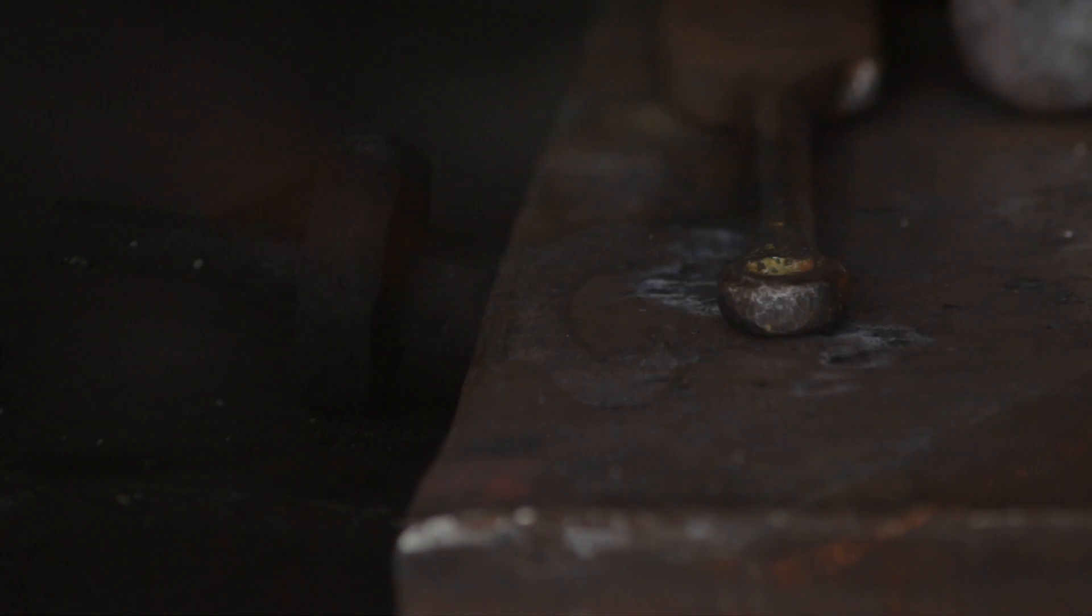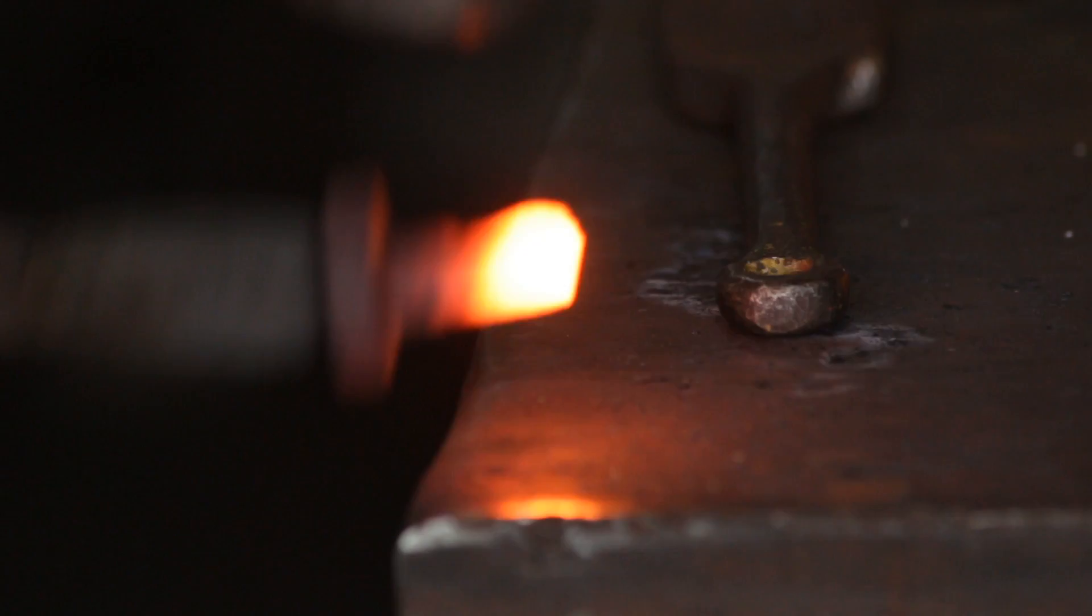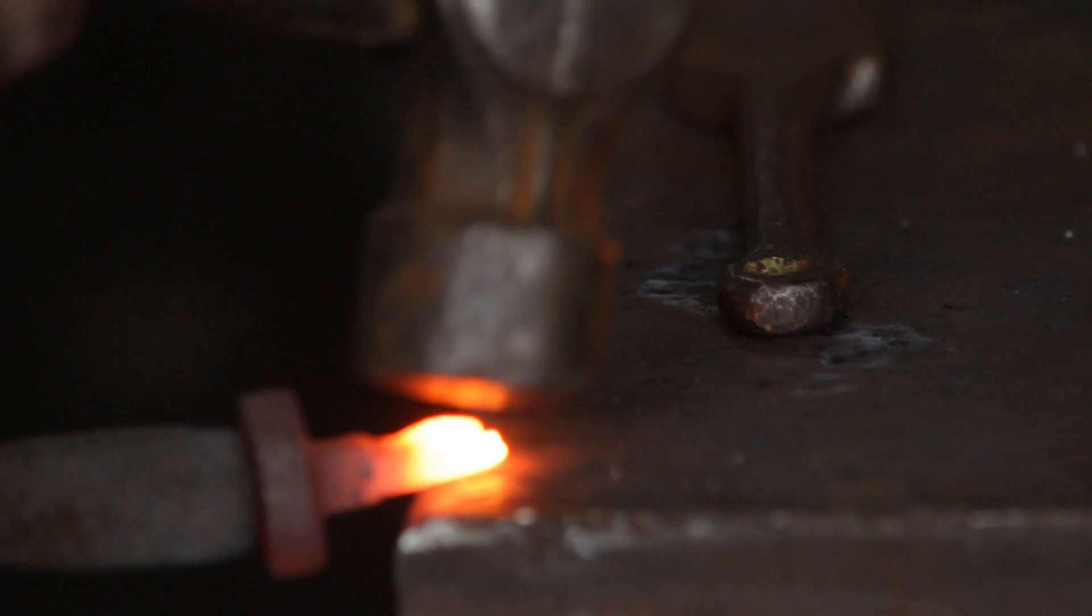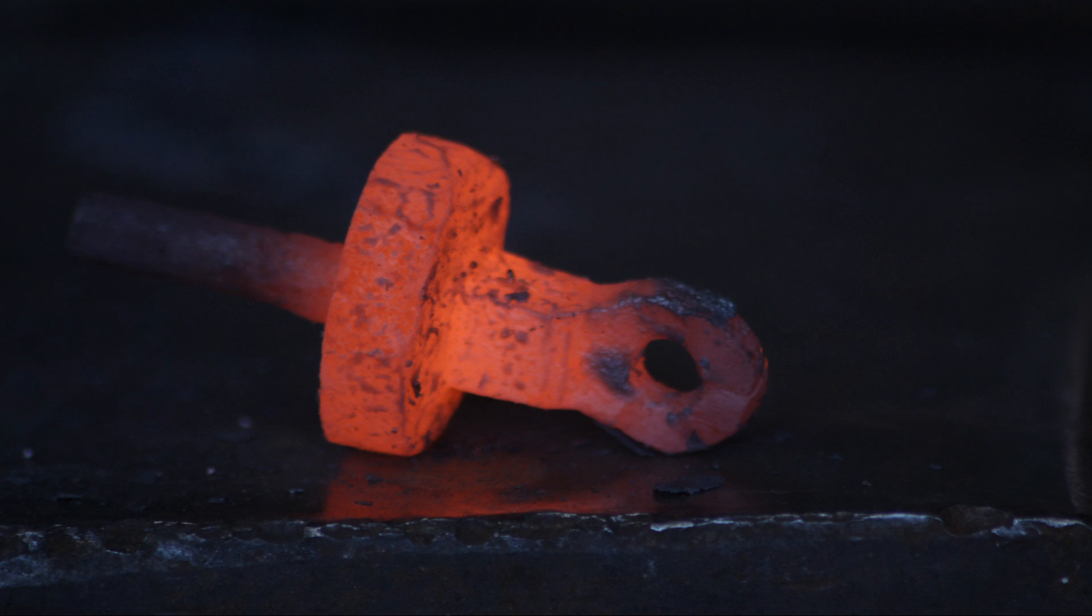All I did was scarf both ends of the split. Like so. Just to get nice welding lines. And then I brought them together in a slightly out of focus kind of way. I do apologize for that. And then taking a short welding heat I just welded them back together. And this is the end result. You can see the weld line but it is solidly welded.